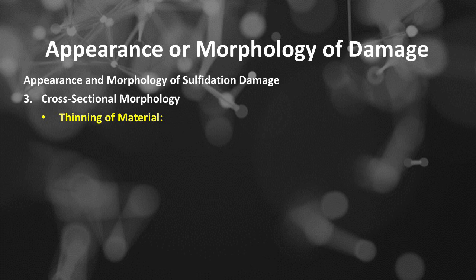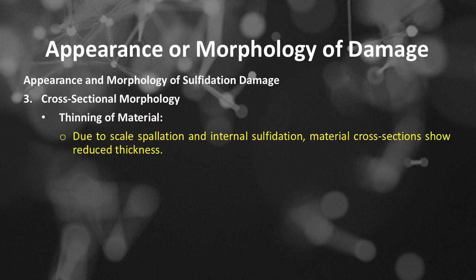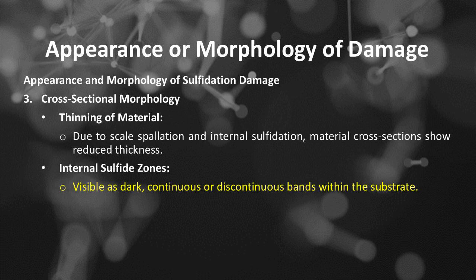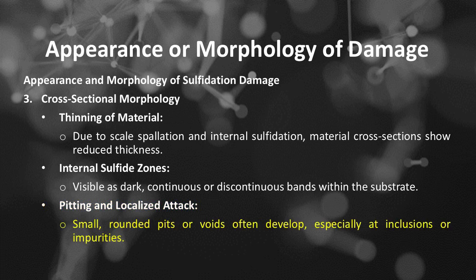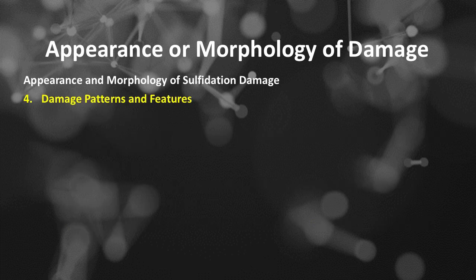Thinning of material. Due to scale spallation and internal sulfidation, material cross-sections show reduced thickness. Internal sulfide zones. Visible as dark, continuous or discontinuous bands within the substrate. Pitting and localized attack. Small, rounded pits or voids often develop, especially at inclusions or impurities. Number 4 of appearance and morphology of sulfidation damage is damage patterns and features.